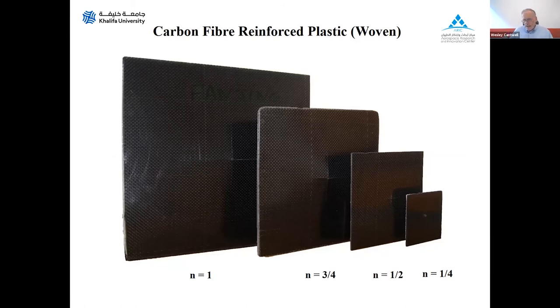And then we encountered carbon fiber reinforced plastic. And this is a woven laminate. It's very much a toughened matrix, and it's a toughened epoxy matrix. And it generally doesn't delaminate very much when it's impacted. It fails in fiber fracture more so than delamination.